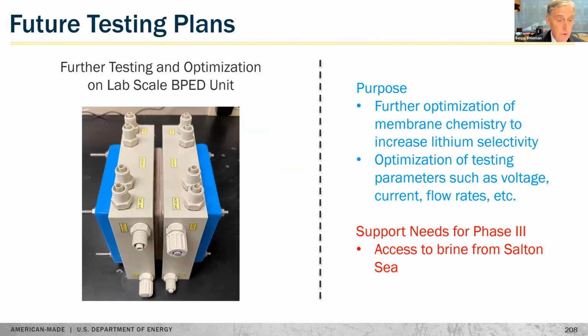And so we're continuing to do work in the laboratory. A lot of that work is aimed at optimizing the membrane chemistry to increase the lithium selectivity, and also to optimize the test parameters, flow rates, voltage, current, et cetera, so that we get the conditions just right for the pilot test. What we need in support for phase 3 is access to brine, representative brine from the Salton Sea that we can put into this system.